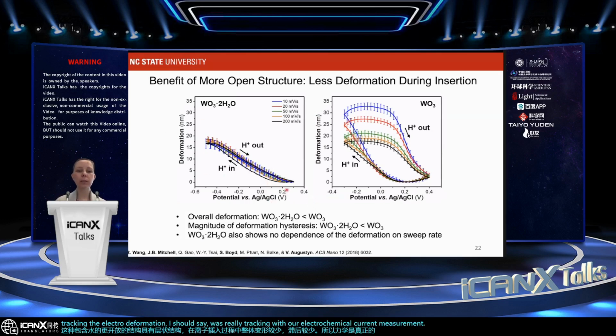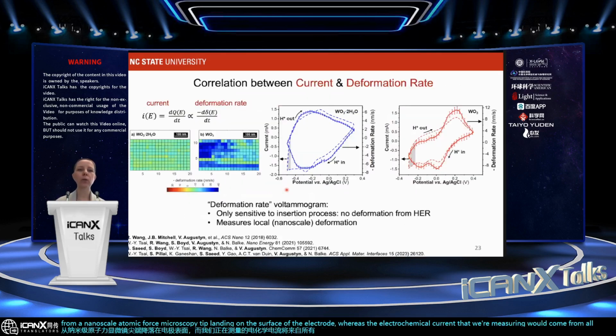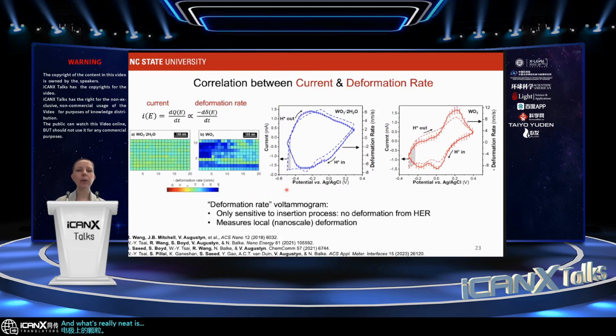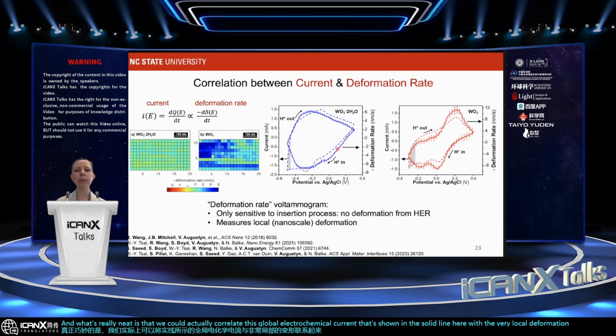So this deformation measurement is coming from a nanoscale atomic force microscopy tip landing on the surface of the electrode, whereas the electrochemical current that we're measuring would come from all the particles on the electrode. And what's really neat is that we could actually correlate this global electrochemical current that's shown in the solid line here with the very local deformation measurement that's coming from a single point on the electrode.